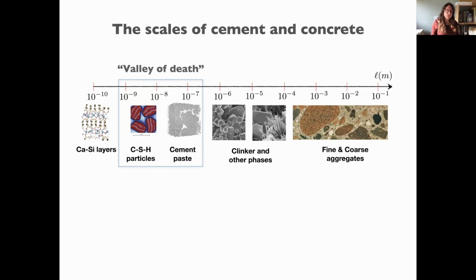So if we start going down on scales as we move towards the center and left side of the bar, we can see different crystalline phases that develop during the hydration of cement. And if we go even further down, we start going into these phases and most importantly into the glue of cement, which is called CSH. This represents calcium silicate hydrates.